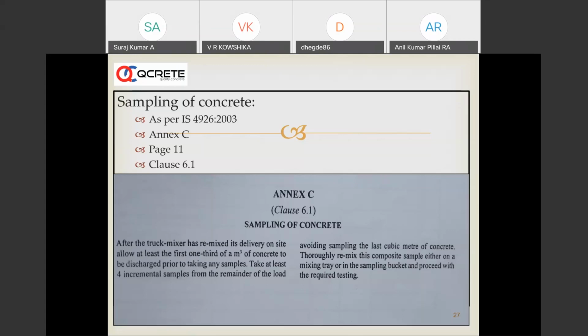This is a very important step because when you are taking a sample, you are taking about 50-60 kgs, which will represent ultimately about 4-5 cubes or 6 cubes at the most, and you are taking the sample from a truck which contains about 6 or 7 cubic meters, which is about 15 tons of concrete. By taking a sample in a non-standard, irregular way, as per the whims and fancies of somebody, it will definitely affect the strength. The strength will be totally different from what it should have been if we don't do the sampling properly. This is what we are talking about in the IS code.